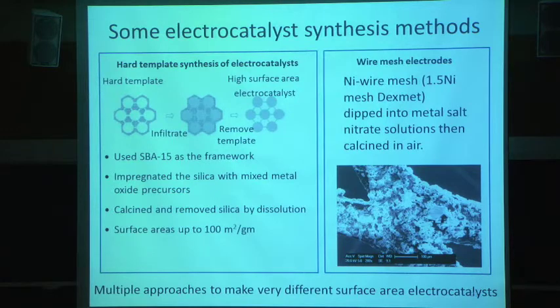So to make some progress in understanding how iron promotes the nickel oxide material, we synthesized a lot of different electrocatalysts. We tried making very high surface area electrocatalysts where we took a hard template like SBA-15, infiltrated it with iron and nickel nitrate salts, calcined it, and then removed the silica by dissolving it. That gave us electrocatalysts in the 100 meters squared per gram range. We make that into an ink, put it onto electrodes, and we can characterize the reactivity. We also looked at some evaporation-induced self-assembly that gave us maybe 30 meters squared per gram.